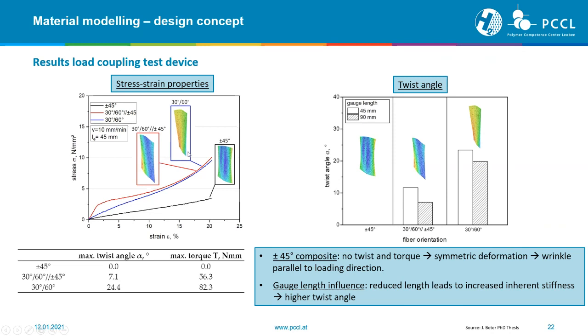The colored pictures that you also see here are not simulation results. These colorful pictures are directly measured. It's the measurement of the surface strain with a camera system. And actually, we are in the phase of directly correlating these simulation results with our test results to also verify this test setup.